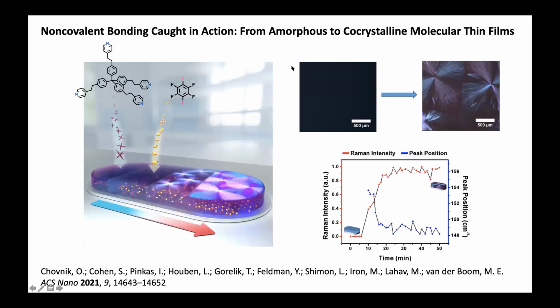So what we did is the following. By vapor phase deposition, we generated films for these kinds of molecules. These films are amorphous. And then in a closed cell, we expose these amorphous films to these kinds of molecules at 60 degrees Celsius, and we follow these reactions. And these nitrogen groups can interact with these iodine groups. And what we see in time under polarized light, first nothing, because you start with basically an amorphous film. And you see here these Maltese crosses appearing, indicating the formation of crystalline material.